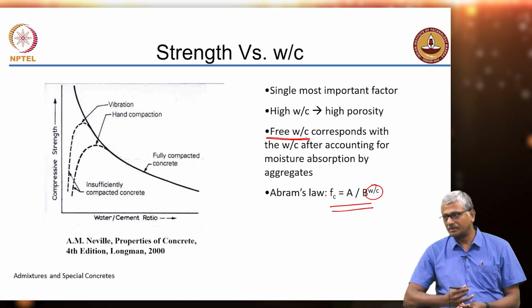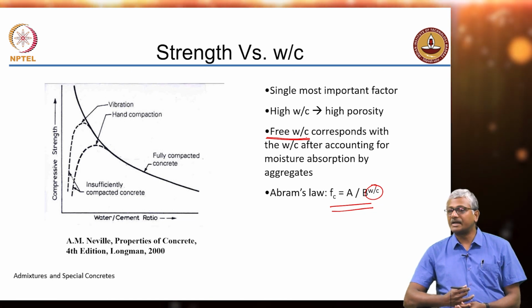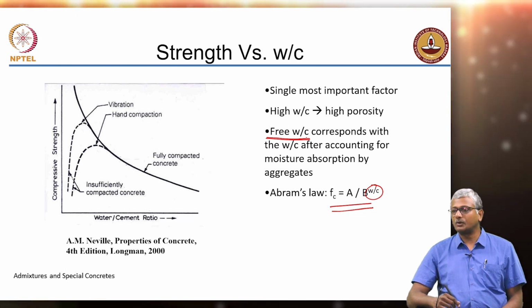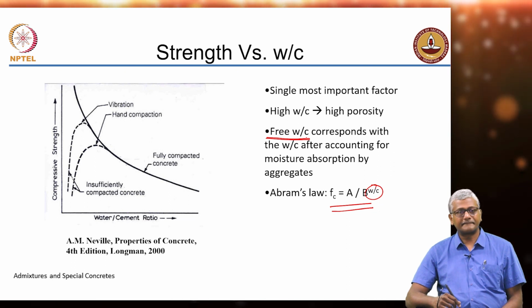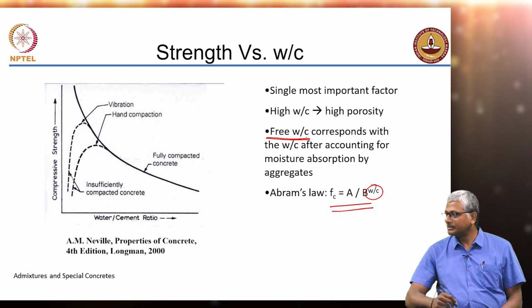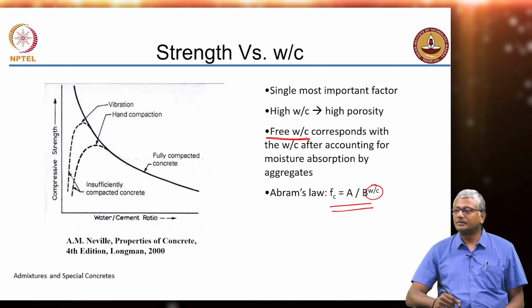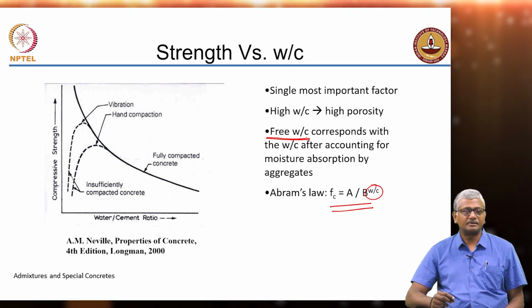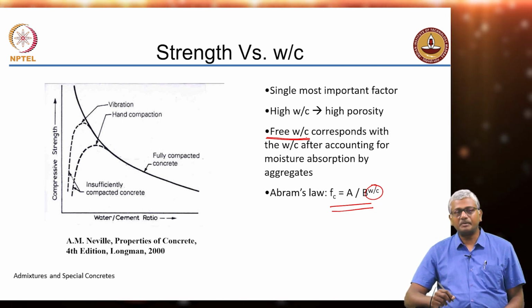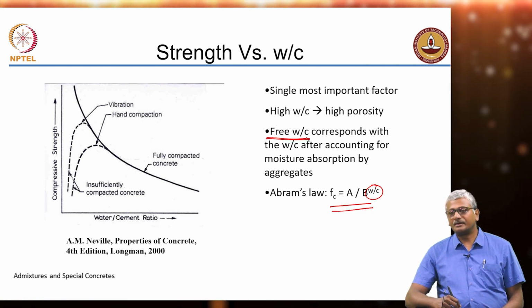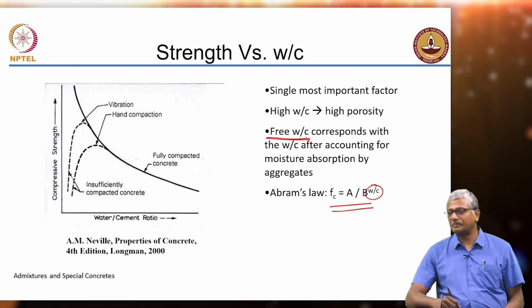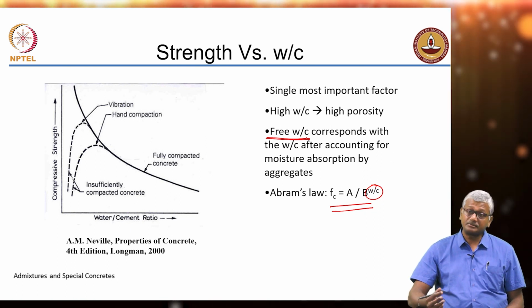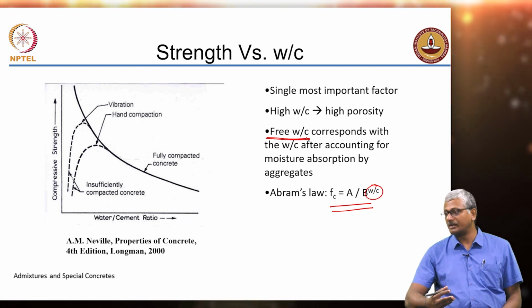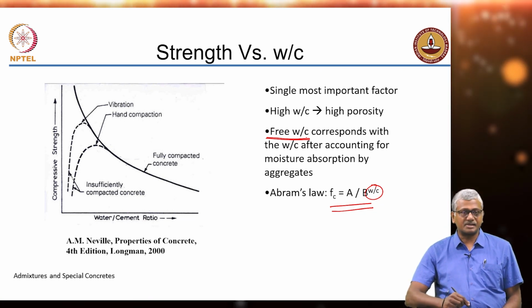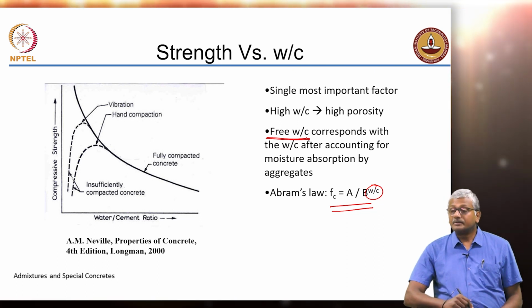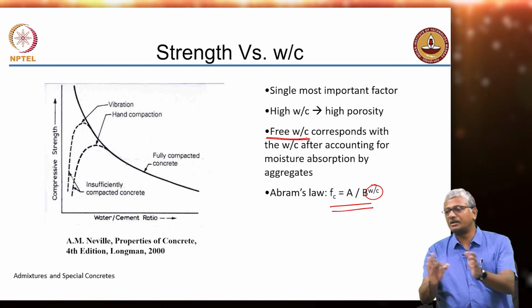For fine aggregate, you may have up to 1% if you have river sand. If you have crushed sand, if you make sand by crushing coarse aggregate, is the water absorption going to be higher or lower? If you use crushed granite or what we wrongly call as M sand, what would be the water absorption? Will it be higher or lower than river sand? Lower? Why? It will generally be higher because when you crush, you produce a lot more fines in the system, and because of the silt size particles, the extent of water uptake by the sand can be significantly high. So, your water absorption typically, if you go to Mumbai for instance, can be as high as 6 to 7%, which makes concrete very difficult to properly design unless you are doing water content measurements from time to time. So, it depends obviously on the extent of moisture absorption, which is dependent on the type of aggregate that you are using.